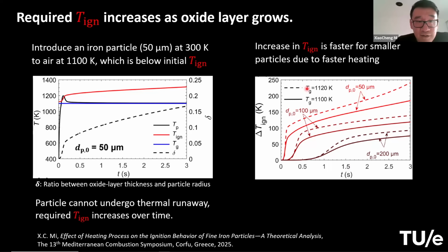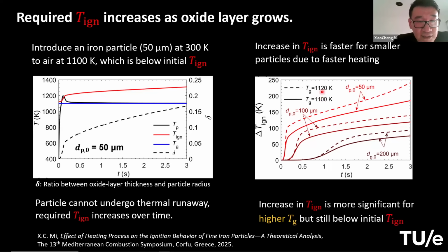And another interesting thing is that if you increase the gas temperature, it starts below the initially required ignition temperature, but as you increase it higher, it gets closer to the ignition temperature. The oxide layer grows, and the required ignition temperature increase is even faster. So this might be a little bit counterintuitive. You think, okay, you get even closer to the ignition temperature, why do you make it even harder to ignite? That's because the oxide layer growth is also faster, right? So this is the key effect.